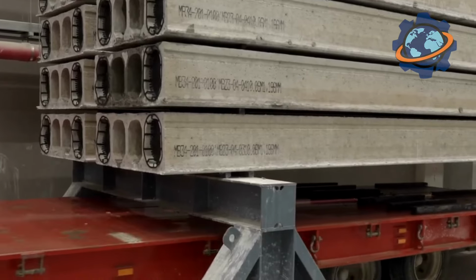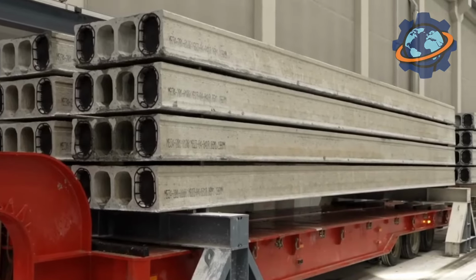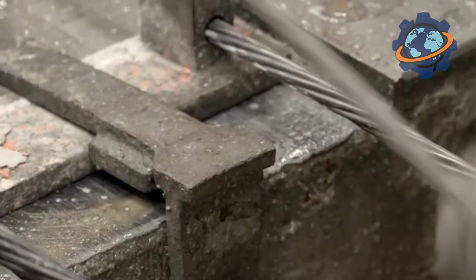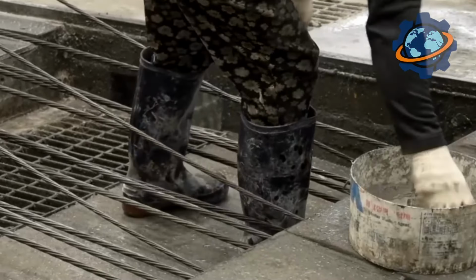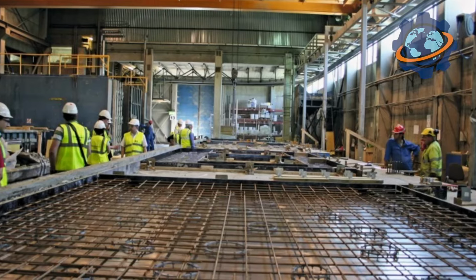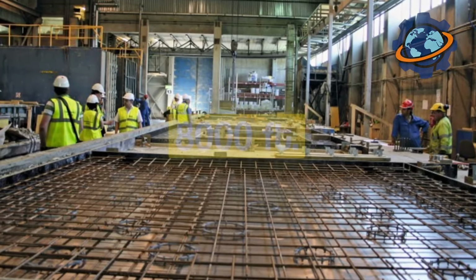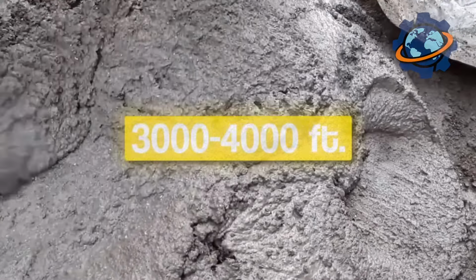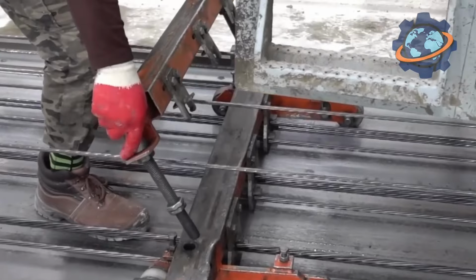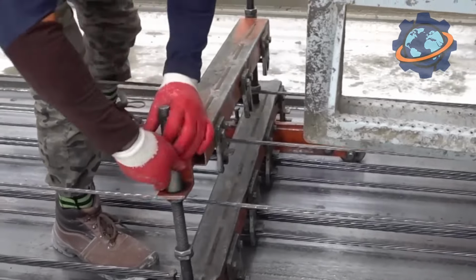But how can such a light slab be so strong? The secret is in those tensioned steel muscles. The concrete used in these slabs isn't what you'd find on the footpath. It's high-strength concrete that can handle pressures over 8,000 pounds per square inch, while standard concrete manages only 3,000 or 4,000. And the steel strands inside are tensioned with such force that they create a constant state of compression within